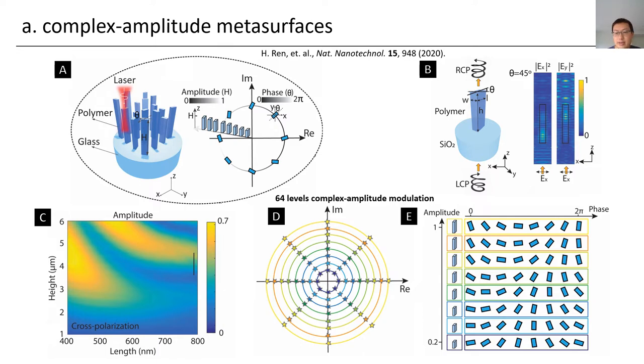Suppose this is the photoresist material, and before the laser interaction, and after the interaction, we have the laser spot here. And, you know, based on the two-photon polymerization, once the laser energy density is high enough, that will induce the photopolymerization that can make this polymer material solid, so that you cannot wash it away during the chemical development process. And then in the end, after this development, we end up with these high aspect ratio nanopillar structures. Even though the material itself has a low index of around 1.5, if you make this aspect ratio correct, you still can accumulate a strong birefringent property.